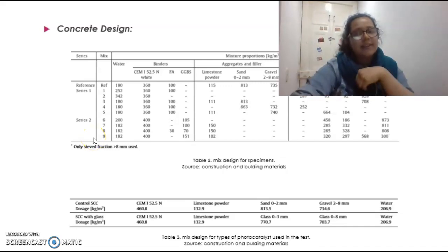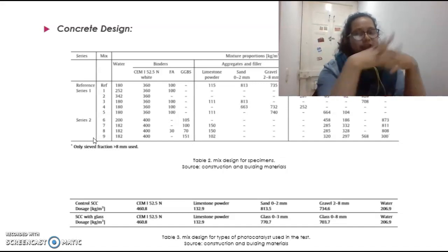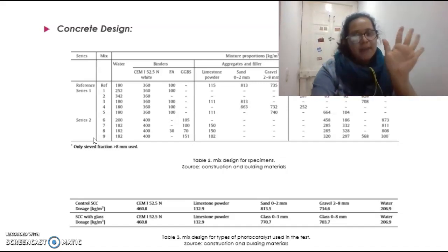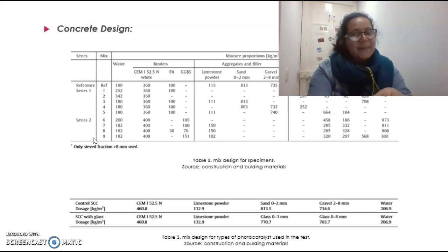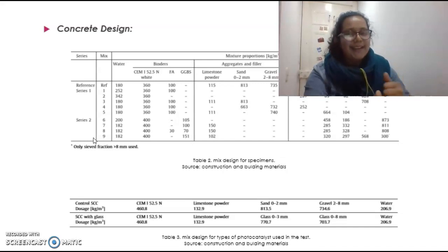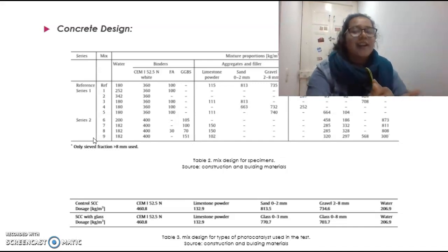Two series were designed and developed, one with washed glass and another with glass in delivery condition. For the first series, 5 mixtures are obtained. The first two are mixtures where the aggregates are replaced by glass, but the first one has fly ash applied as a cementitious material. Mixtures 4 and 5 are mixtures of glass aggregate and common aggregate where the sand is replaced by glass powder or coarse aggregates.